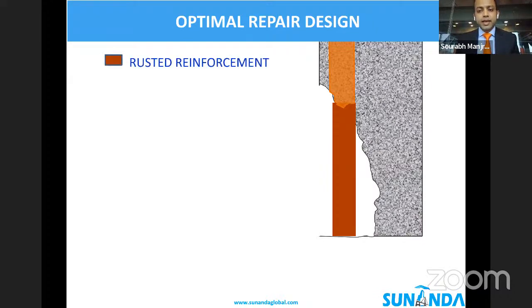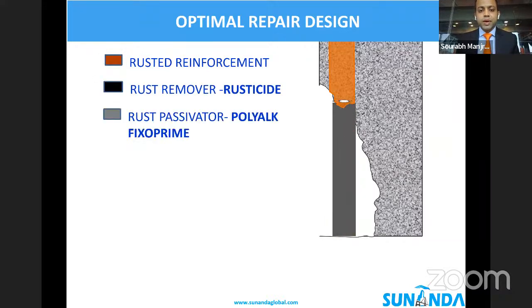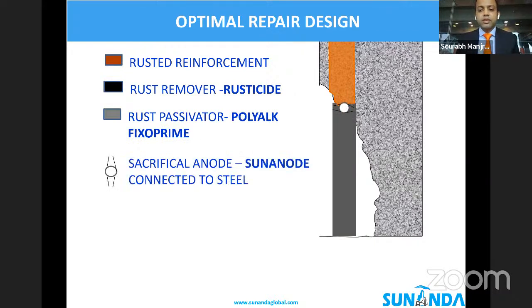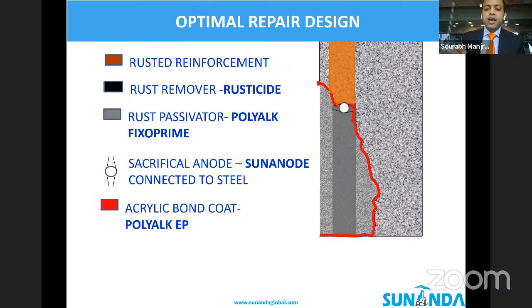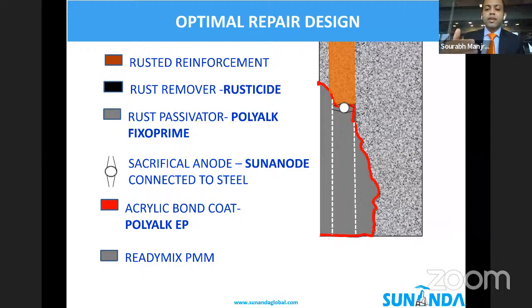So everything else remains the same, the rust removal coating, the rust passivating coating. The only change is that we also connect the sacrificial anode at the junction of the patch repair and the embedded steel. So now, instead of the embedded steel becoming the anode, we have connected an external anode, which will in turn protect the embedded steel, as the anode will be sacrificing itself, corroding itself, and protecting the embedded steel. And in turn, you will not encounter this phenomenon of ring anode corrosion, and you will be able to ensure your designed service life for your retrofit.